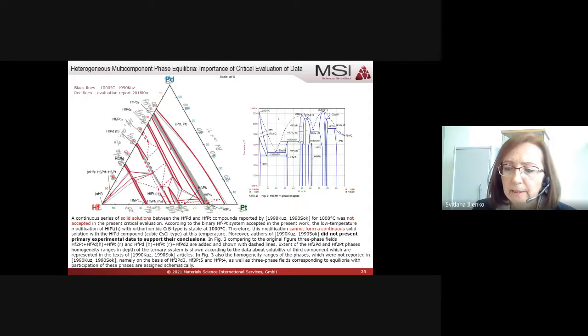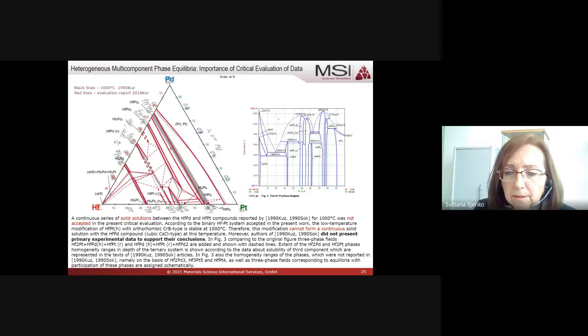And obviously, the crystal structure of the low temperature phase is different from the crystal structure of the hafnium palladium phase, while high temperature phases have the same structure. But here we are at 1000 degrees in the binary system, and here indeed we have only the low temperature phase. And this is the task already of our authors, to see that, yes, this is not possible, so they cannot form a continuous series of solid solutions in the ternary if they have not the same structure.